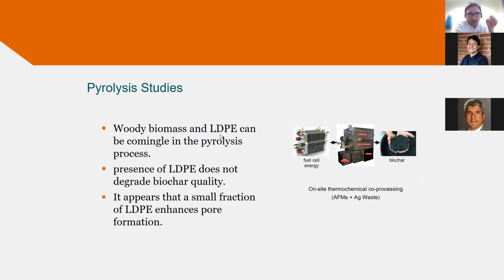So woody biomass and LDPE can be commingled in the pyrolysis process. The presence of LDPE does not degrade the biochar quality, and it appears to be a small fraction. It appears that the small fraction of LDPE actually could enhance pore formation. But let me stop here for a second and let Tom give us a quick update on that.